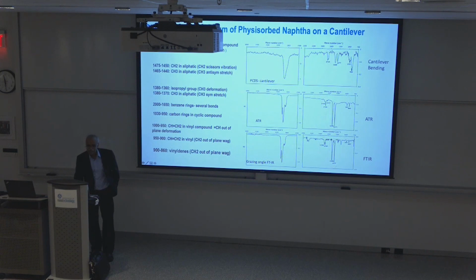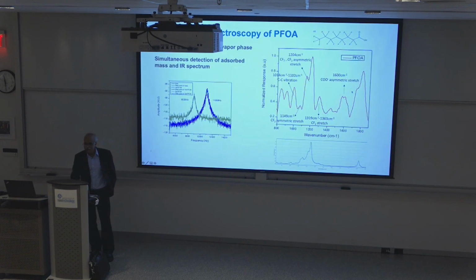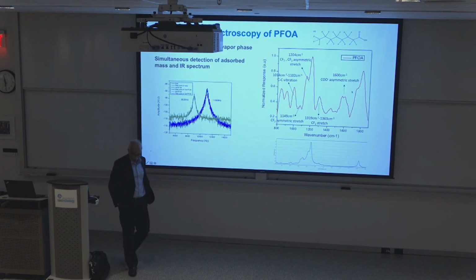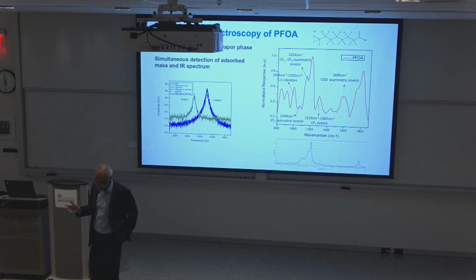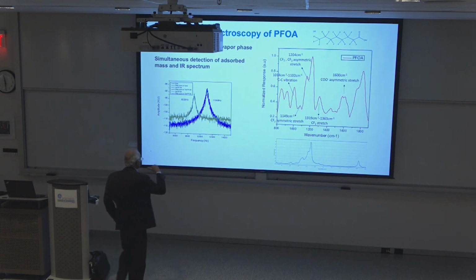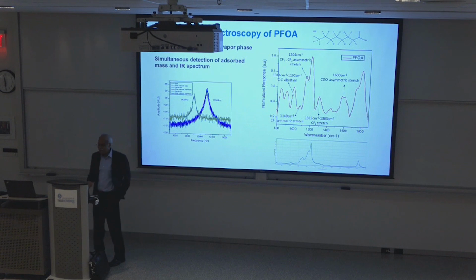Another example, look at the PFOA. Now we have lots of interest in PFAS, so PFOA is one of the problem ones. Again, we absorb the PFOA on the cantilever, and then look at the cantilever bending as a function of different wavelength, and you can see all the different peaks. And this is the NIST standard spectrum of PFOA, and we can identify all these things. And we can see that there are more features with this approach than with conventional FTIR.